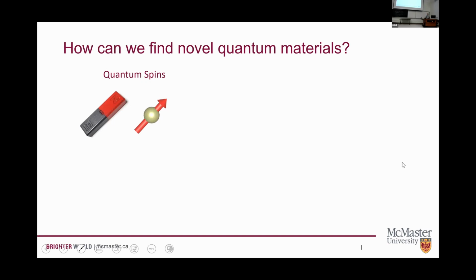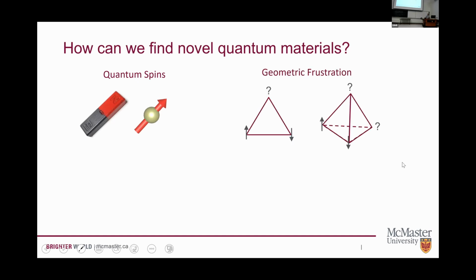One of the things we can do is look for materials that have quantum spins. So the smaller we make our magnetic moments, the more essentially quantum mechanically they behave. We can try and design materials that are based on crystal structures that have geometric frustration. So in other words, you pick a material where magnetic interactions favor one type of alignment, which is incompatible with the crystal structure that they're based on.